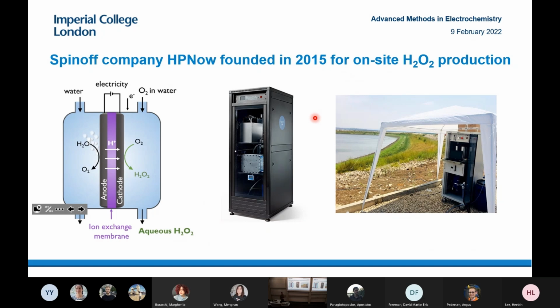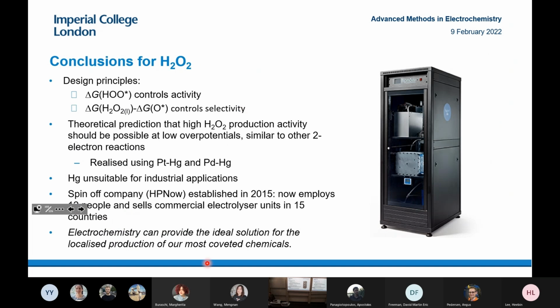The only downside was what we realized when we spoke to people in the industry: there's absolutely no way you're putting any mercury near the electrolyzer. Nobody wants to use mercury, but we've still proven that you could actually get really high activity and selectivity for hydrogen peroxide without compromising. You get high selectivity without compromising in activity. So we later found we could do this in other materials as well. And we're now selling these hydrogen peroxide units in 15 different countries. This is a direct impact of a collaboration between experiments and theory.